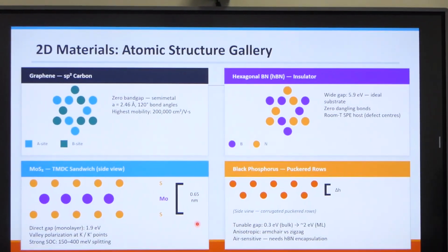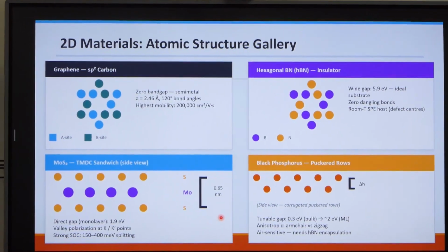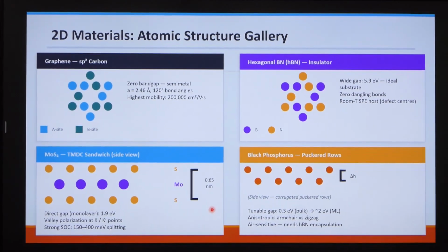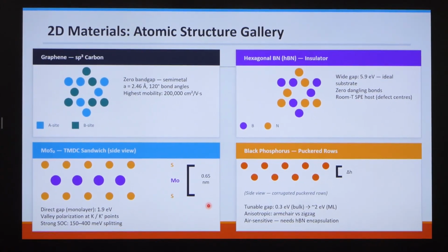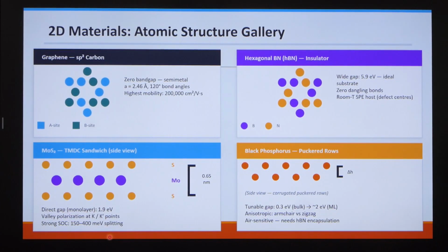Coming to this: sp2 graphene has zero band gap. Then the TMDCs, which are MoS2, WS2, MoTe2 and all those. We have a layer with two chalcogens in between one transition metal, and a direct band gap here, and valley polarization at this point. And black phosphorus. So these are different, and this is hexagonal boron nitride, which has a wide band gap, sometimes 6 eV or 5.9 eV, and it is an insulator, but it has many properties.